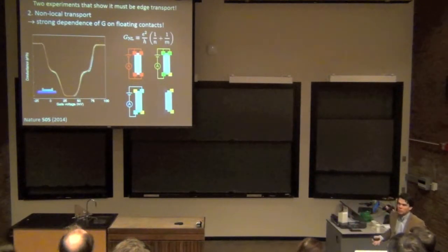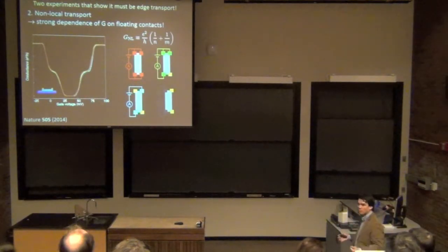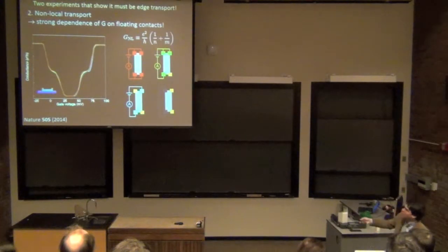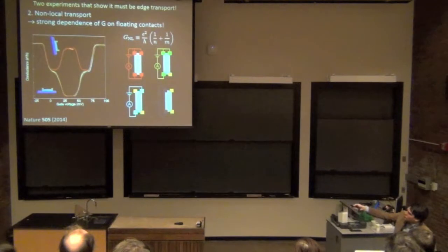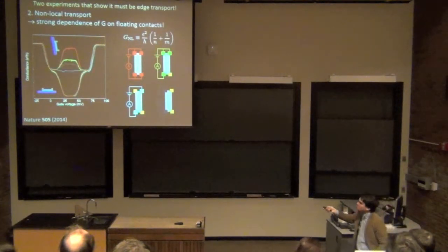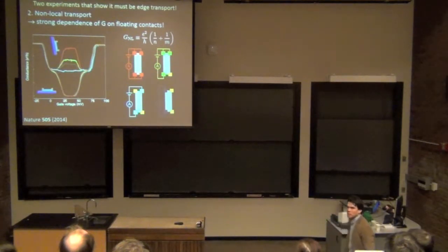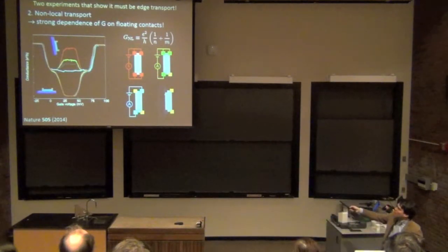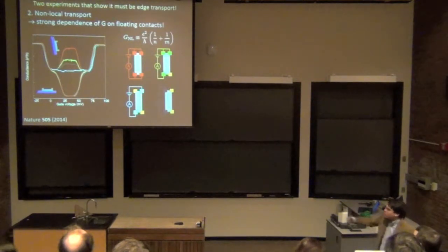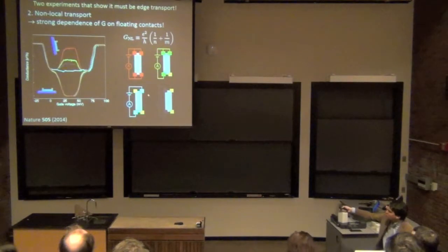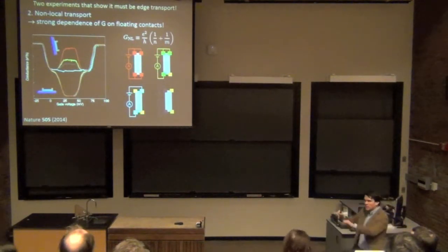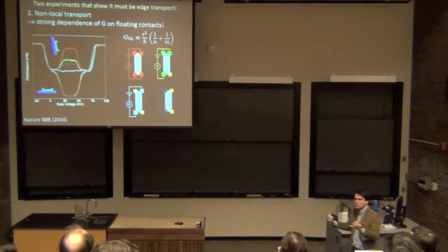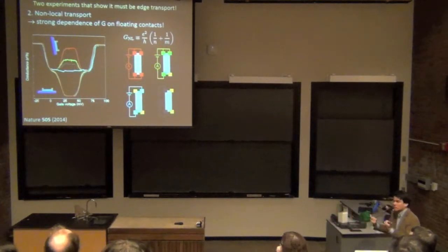The yellow here just means that we're not using that contact, it's just a little dab of metal on the edge of the sample. And what we see in the conduction is that for this normal two-terminal transport, we see almost 2e²/h conductance, but then as we begin to float contacts, we see a marked decrease in the conduction. What's happening is that one of the edge states is equilibrating in one of these contacts. And so when you have two edges in series, you have two quantum resistors of h/e² in series with one another.